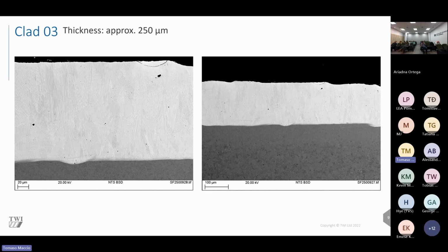Also, when using higher power, sometimes you might get gas pores. The lower melting point alloys within the alloy can boil off and vaporize, so that can be an issue as well. But this sample here is most desirable, with very minimal defects. You can see there are some small defects over here, but judging by the scale bar, they're not over 5 microns in width, and then there are some tiny pores here. You can also see that the grain structure is very columnar, which is desirable for the coating compared to the substrate. The next few slides will demonstrate nicely the heat affected zone and the low dilution as well.